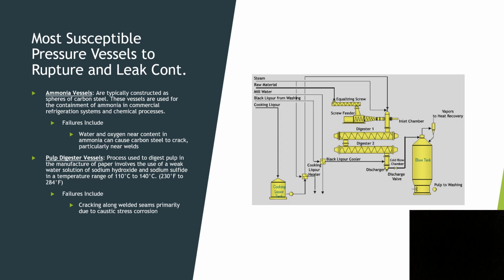The most susceptible pressure vessels to rupture and leak, continued. The ammonia vessels are another one, typically constructed as spheres of carbon steel. These vessels are used for the containment of ammonia in commercial refrigeration systems and chemical processes. Failures include water and oxygen content in ammonia, which can cause carbon steel to crack, particularly near welds.